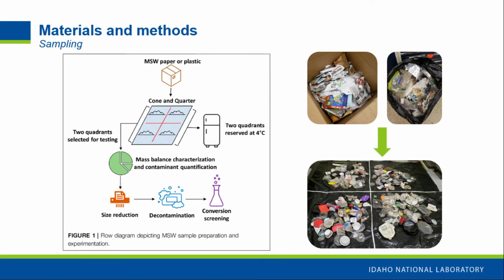Because we had two different streams, mixed paper and mixed plastic, we used two different conversion methods to screen our performance. For the mixed paper, we were using a low temperature conversion, which is enzymatic hydrolysis. And then for the plastic stream, we're using microwave assisted pyrolysis.